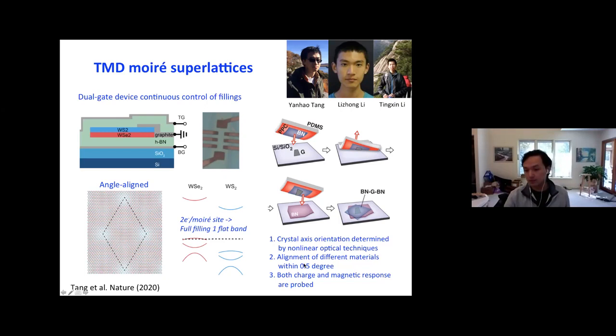And to do that, we use a nonlinear optical technique, which is a polarization-resolved second harmonic generation technique, which can help us map out the crystal orientation of each layer first. Then we align them within about 0.5 degree accuracy to make the heterostructure. And 0.5 degree actually sounds terrible for twisted bilayer graphene, because if you're off by 0.5 degree, you completely lose the magic angle. But again, here there's no magic angle in this system. And because of the lattice mismatch, a 0.5 degree mismatch plays little role, and the physics is very reproducible from device to device.